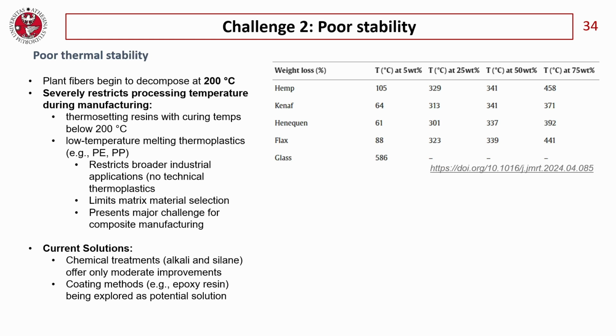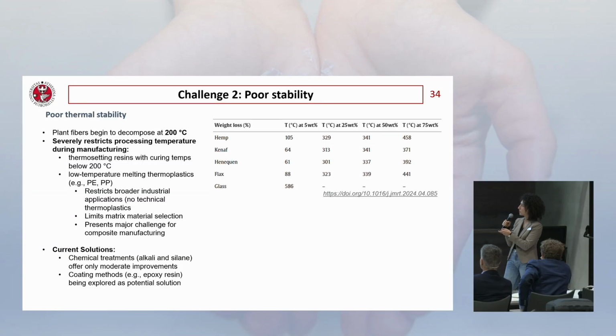Okay, moving on, the second challenge is instead the poor thermal stability. Again, 200 degrees is set as the maximum temperature at which we can process the natural fibers. This, of course, is a problem with, again, engineering thermoplastics, because it's not a problem with thermosetting resins and low melting temperature thermoplastics.